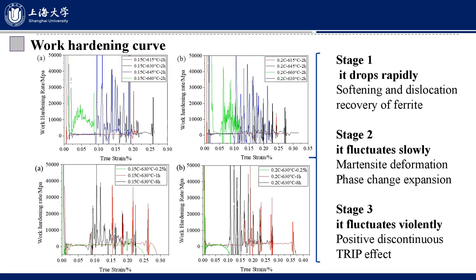This slide shows the work hardening curve of the steels. It shows three stage characteristics. At the first stage, it drops rapidly. Softening and dislocation recovery of ferrite is the reason. At stage 2, it fluctuates slowly, due to martensite deformation and phase change expansion. At stage 3, it fluctuates violently. Positive discontinuous TRIP effect occurs.